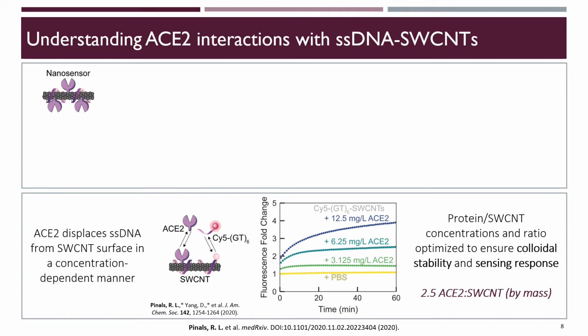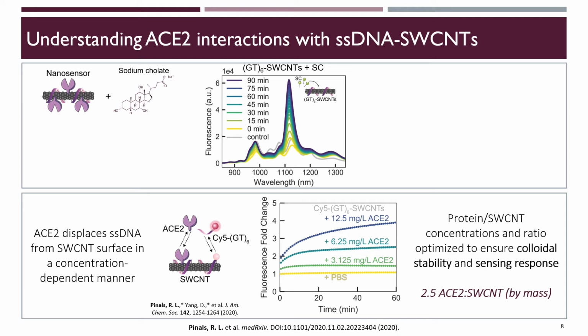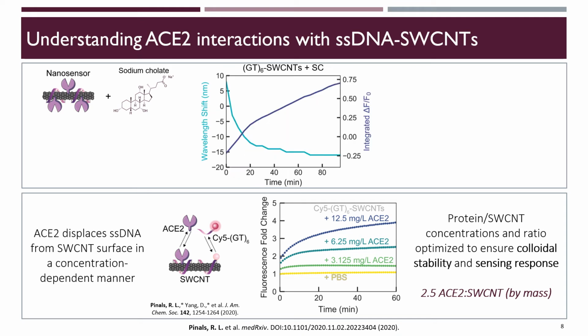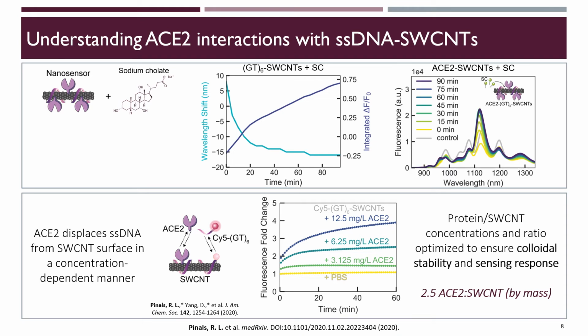In an effort to further deconvolute the interactions occurring at this protein-carbon nanotube interface, I next employed a surfactant displacement assay. This is based upon addition of surfactant, here sodium cholate, that coats any solvent-exposed carbon nanotube surface and can displace low-affinity molecules from the surface. When sodium cholate adsorbs, this causes exclusion of water from the nanotube surface and produces a large increase in fluorescence and blue shift. Before ACE2 incubation, addition of sodium cholate does indeed elicit a large blue shift and a sizable increase in fluorescence. And here I'm summarizing these spectra as a function of time. Upon passivation with ACE2, these spectral changes were drastically reduced, as I'm showing here.